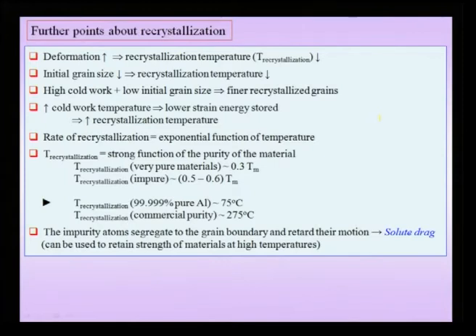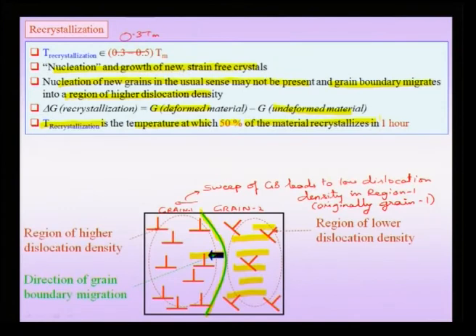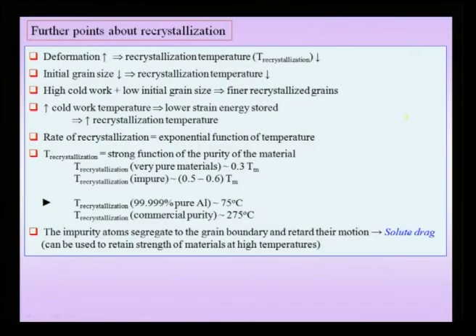A few points about recrystallization temperature. So, once again, what is the definition of recrystallization temperature? It is the temperature at which 50% of material recrystallizes in 1 hour. If you increase the amount of deformation, the recrystallization temperature decreases. That means the more deformation I give, the lower the temperature I have to heat to in order to form these strain free crystals. If my initial grain size decreases, the recrystallization temperature decreases.